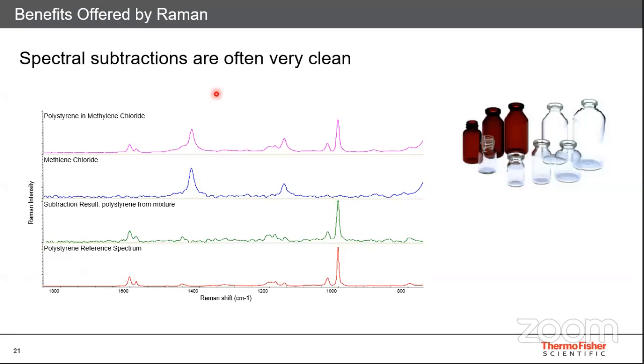Another important thing is that the spectral subtractions are very clean. The reason behind this is that Raman is basically for the backbones, and therefore it has less absorption in the polar groups, which actually result in hydrogen bonding. So it has an effect on those kinds of peaks. If you change the solvent, the change of solvent has an effect on the absorption spectra in infrared spectroscopy. Well, in Raman, what we are seeing are the covalent bonds, C-C bonds, where there is not much effect of the solvent or the environment on those groups, and therefore you see very clean spectral subtraction in Raman spectroscopy.